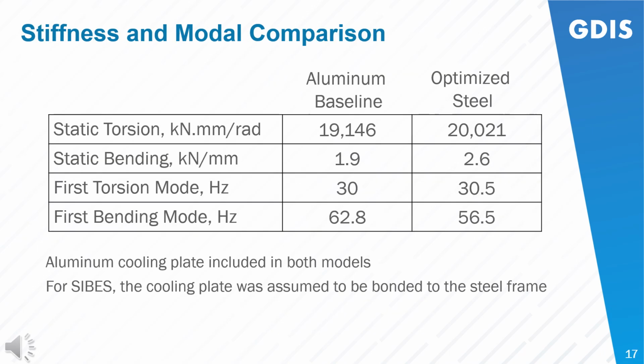Looking at the stiffness and modal comparison between both the aluminum baseline and the optimized steel, you'd note that for the static torsional stiffness, measured in kilonewton millimeter per radian, the steel is slightly better. For static bending, measured in kilonewton per millimeter, the steel is appreciably better. For the first torsional mode, measured obviously in hertz, the steel and the aluminum are almost the same. And then for the first bending mode in hertz, the steel is slightly below the aluminum baseline.